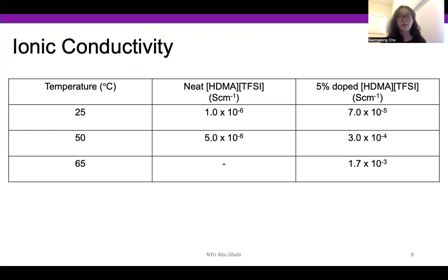more disordered plastic phase. And then also in the 5% dope sample, you can see that the ion conductivity is higher than the pure sample at room temperature, and also it increases with increasing temperature. So it is hypothesized that the pure sample increases ionic conductivity as it moves from a more rigid phase to a disordered plastic phase. And for doping, it increases the number of diffusive species and increases the number of vacancies, leading